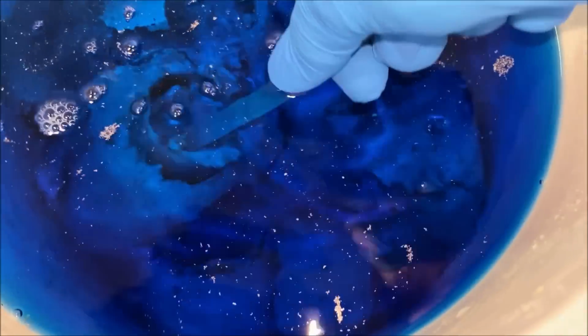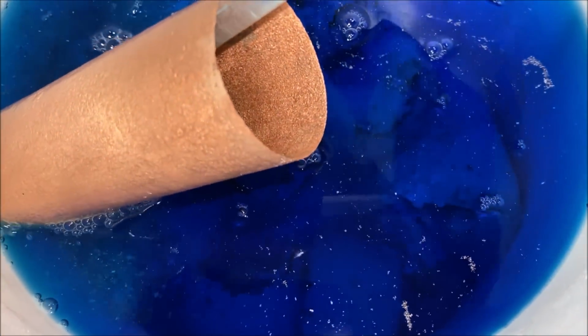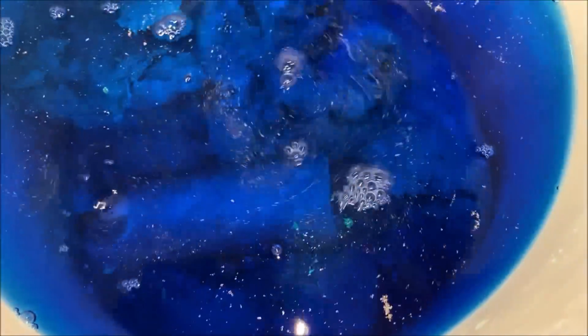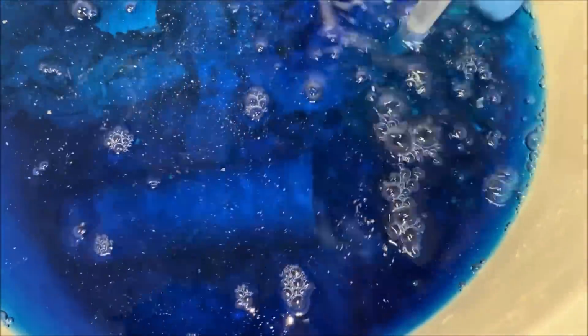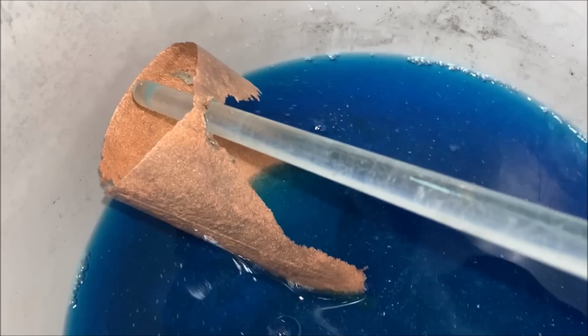And what I do is I take the silver that I recover from my gold refining, and I put it in this bucket, and it's a silver nitrate and copper nitrate solution. Then I add pieces of copper in here, and the silver cements out onto these pieces of copper, and the silver forms a gray powder that falls to the bottom of the bucket.